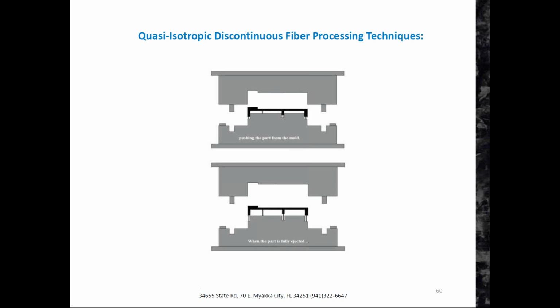It's flowable, so you can have huge variations in thickness. The tooling can be done reasonably inexpensively, and to give you an example, we can tool up a small 32-inch long UAV, let's say. Everything, the entire fuselage, the booms, the tail sections, the kind of thing you saw in our brochure, for probably in the neighborhood of around $35,000. The tooling, we could get 5,000 shots out of that tooling, and we can cycle it every 10 minutes, and in some cases as little as 5 minutes.